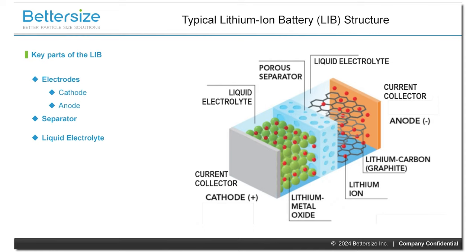Surrounding everything in here you see is the electrolyte medium. There's a pool of a liquid electrolyte here. This electrolyte is a component that has many roles, primarily ion conduction. The electrolyte carries positively charged lithium ions through the separator and transfers these ions back and forth between the 2 electrodes, causing the battery to charge and discharge. Common electrolytes are composed of salts, solvents, and additives, such as lithium hexafluorophosphate, lithium perchlorate, lithium tetrafluoroborate, lithium hexafluoroarsenate. These are dissolved in organic carbonates with carboxylic ester additives to help dissolve the lithium salt.